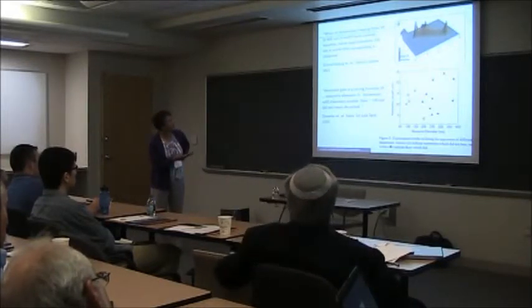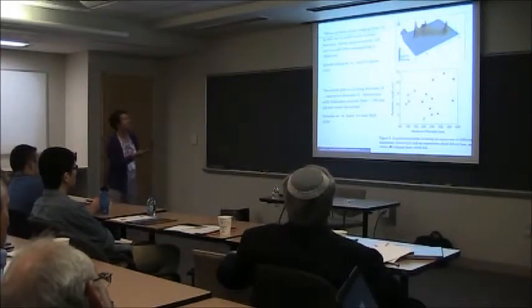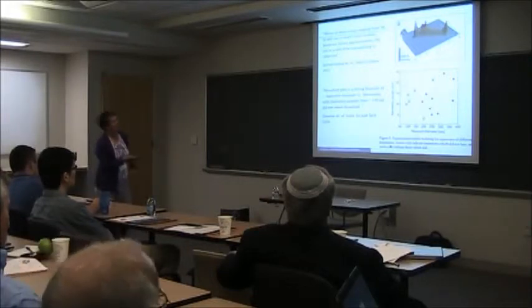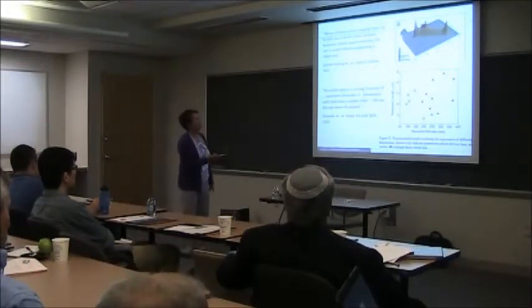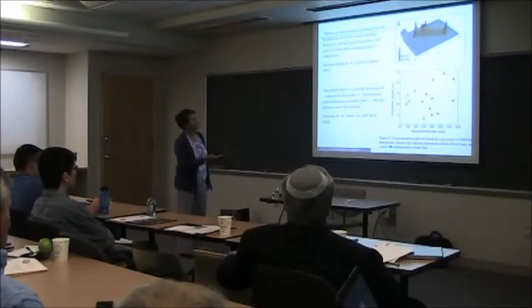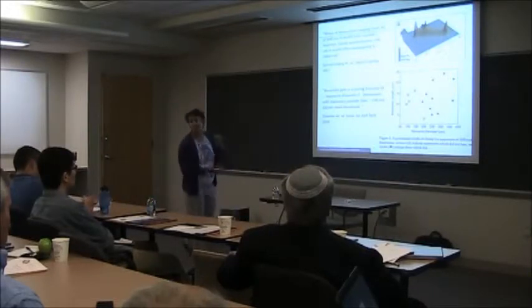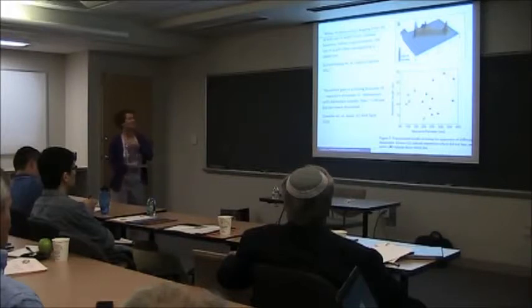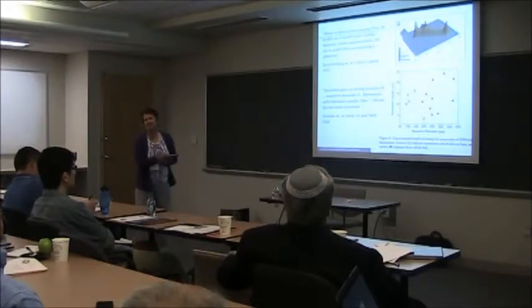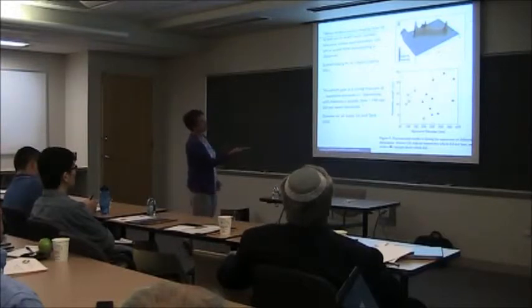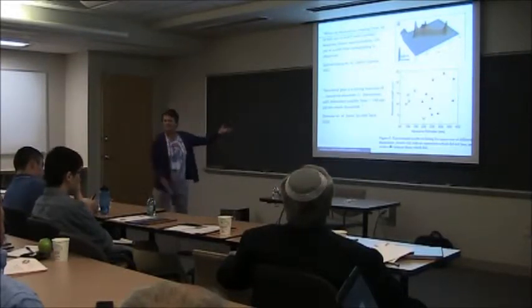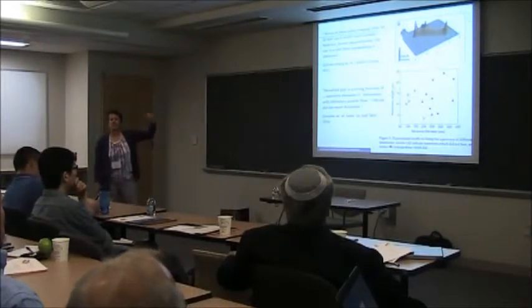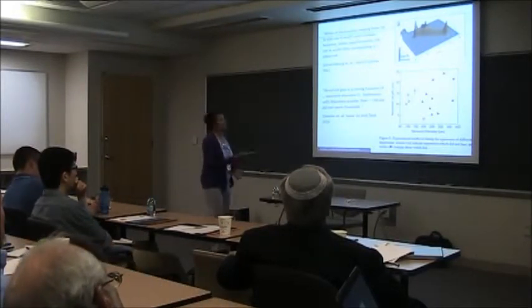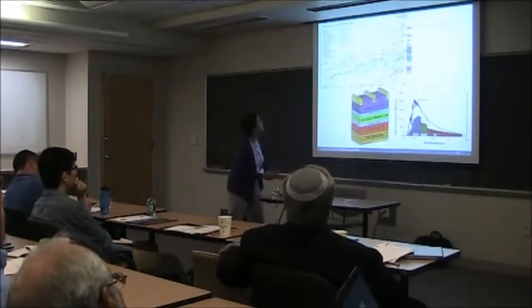There's an interesting paper. Again, you see this kind of phenomenon when people do more standard PL imaging. They were making nanowire lasers, and this is the nanowire length in microns, the nanowire diameter, okay? If you just focus on the diameter, black solids indicate that they got the thing to lase, and the open circles indicate that it didn't lase. You notice, obviously, that the thicker ones were able to lase, the thinner ones did not. This would be one explanation, that effectively your internal alpha may well go up with diameter. So it may explain that information.